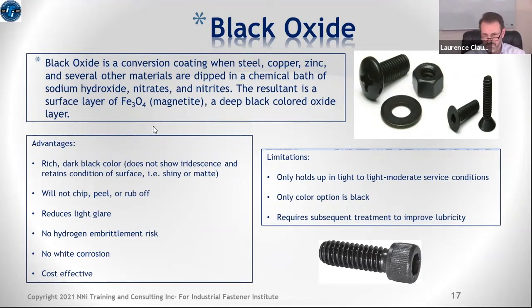It's not going to rub off. There's no hydrogen embrittlement risk. One of the other strong advantages of black oxide is it reduces light glare. It basically doesn't reflect. And so it's very commonly used in defense applications on, say, maybe a stainless steel part where a manufacturer of a tank doesn't want a nice shiny stainless steel fastener on the outside of the tank giving away the position of that tank. And so they might get black oxide coated, which will reduce or eliminate the potential for reflection.